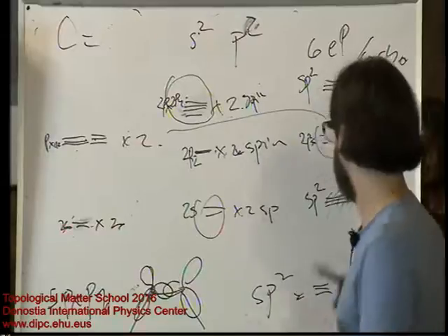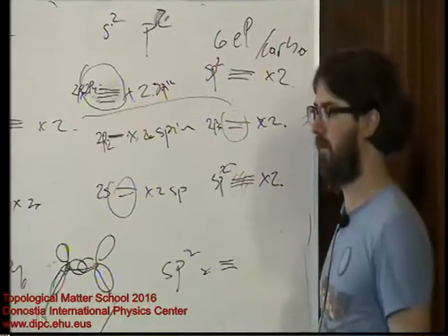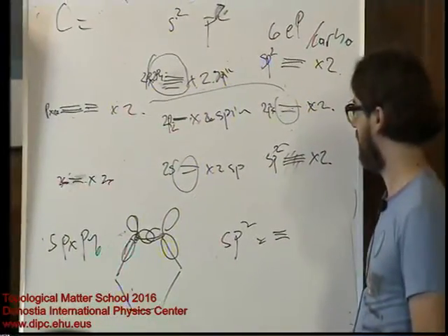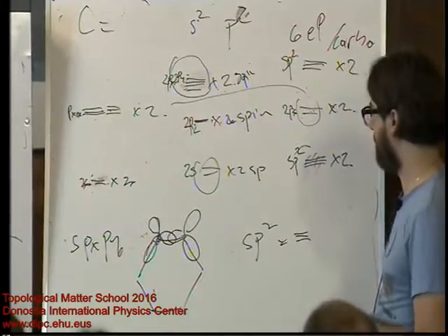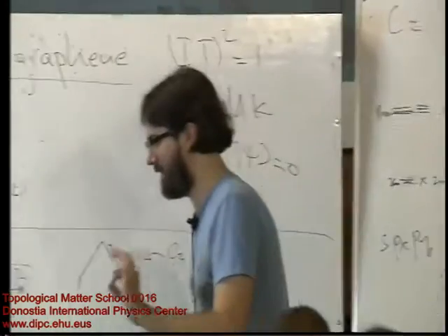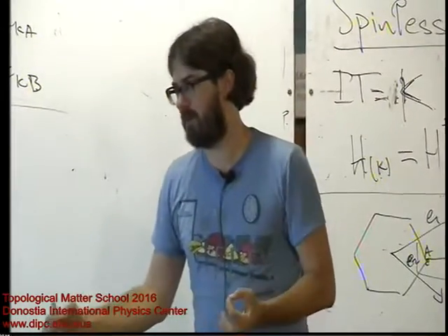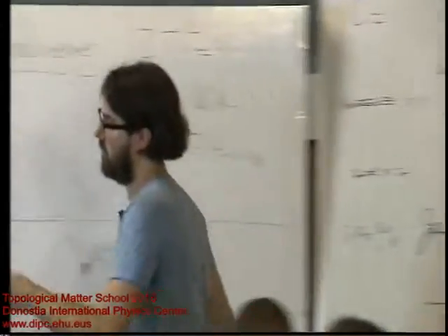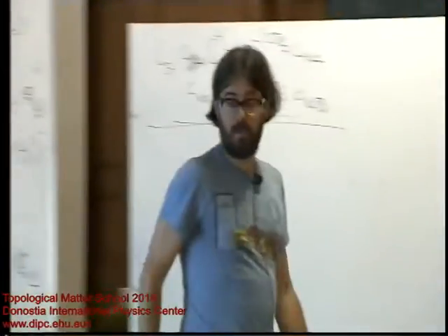Now you can do more things in graphene. Does this hold for all the lattices with C3 symmetry? A very good point. It holds for all the lattices with C3 symmetry and inversion and time reversal if you have pz orbitals or s orbitals. What happens is that this representation 1 here does show up in sp2 orbitals.